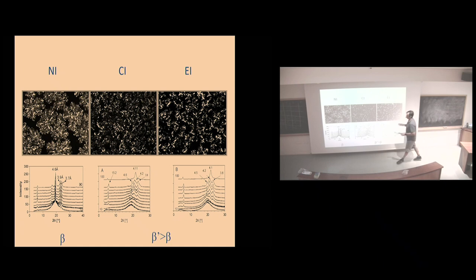Now, if you look at the microstructure, it seems that you have more spherulites in the non-interesterified one, more of the spherulitic growth. You hit it with a catalyst, and you get maybe smaller clusters, and maybe smaller crystals. But one of the characteristics is that in the non-interesterified, now you know, 3.7, 3.9, 4.6, beta, triclinic. So triclinic, and then you dilute it with oil. It doesn't matter how much oil you add, it's the same pattern. You get the triclinic form. You remember how we learned that the triclinic form was grainy, high melting, not good for food products? You saw that yesterday. So there's no change in the polymorphism upon dilution.